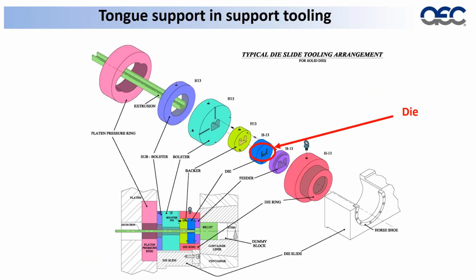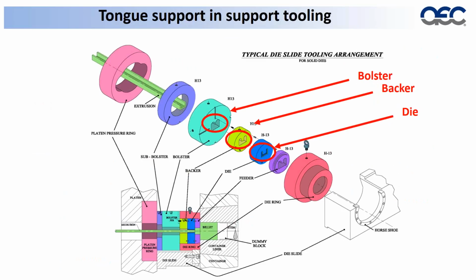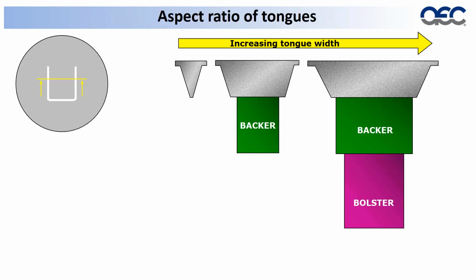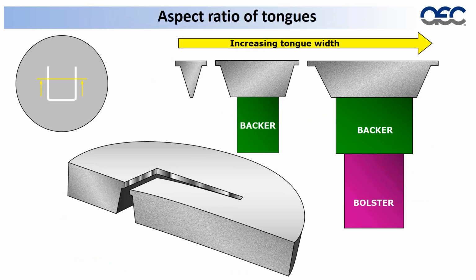When you look at the components of the tool stack itself, what we have is the die, which is the original shape-forming mechanism for the extrusion. We have the backer, which we like to get up inside of the complicated tongues to prevent them from pushing through or breaking or distorting. And in some cases, we actually have the bolster, which we run tongues up in. Depending upon the shape, you'll notice that there's quite a variation of tooling costs involved. And again, that is because of the tooling requirements and based a lot off the aspect ratio of the tongues.